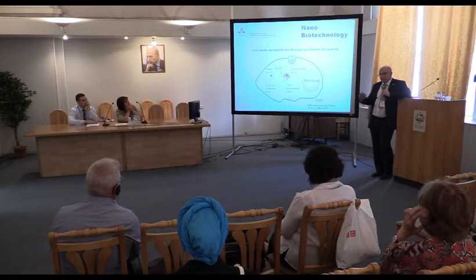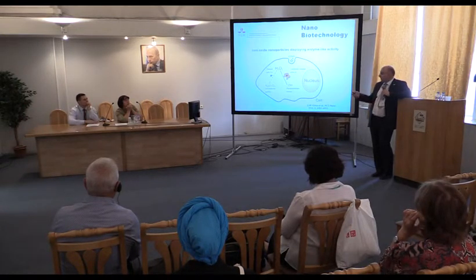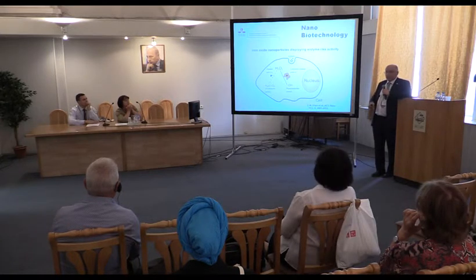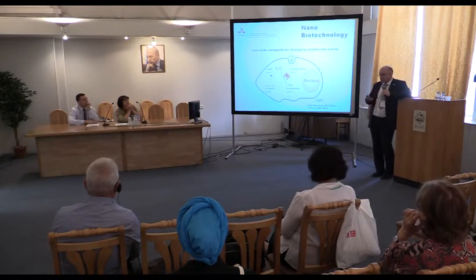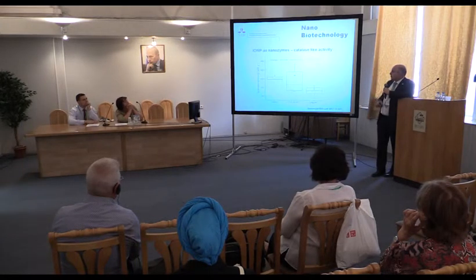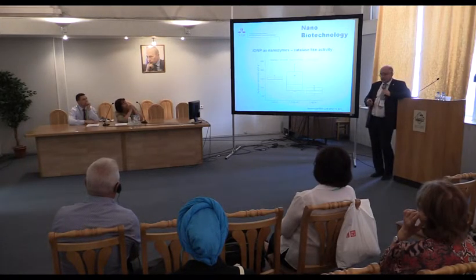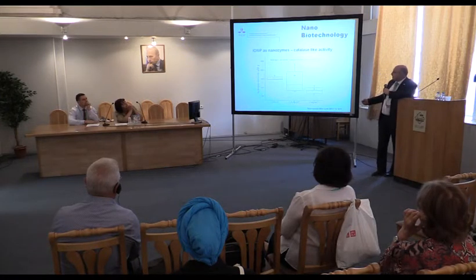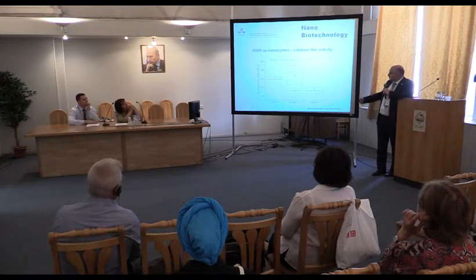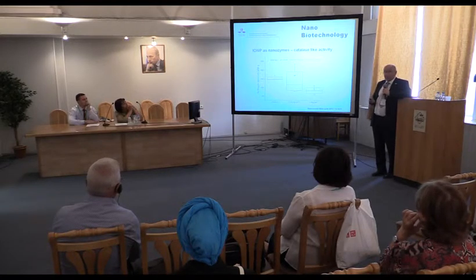It will relieve them from stress, for example, drought stress, when there is too little water and plants start to produce reactive oxygen species. And this kind of activity is very dangerous because it will oxidize plants more and increase the stress. So when iron oxide is doped with yttrium, this maghemite structure is behaving like a catalyst. It is actually decreasing the content of hydrogen peroxide in the plants very distinctly, and more when there is a high concentration of iron oxide particles. We have, of course, checked against pure iron salt.